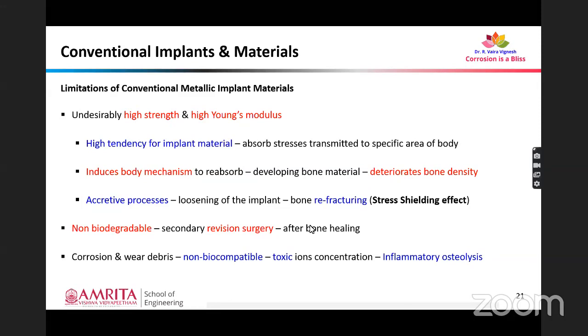Added to that, these materials are non-biodegradable in nature too. It means we have to do a secondary revision surgery after the bone heals completely, which also has a huge impact on the wellness of the patient. And added to that, the corrosion and wear debris are non-biocompatible in nature. This leads to accumulation of toxic ions within the bone region, which leads to inflammatory osteolysis. So we should ensure that we have biocompatible corrosion and wear debris even when the implant is placed inside the human body for an extended period of time, to avoid the inflammatory osteolysis condition.